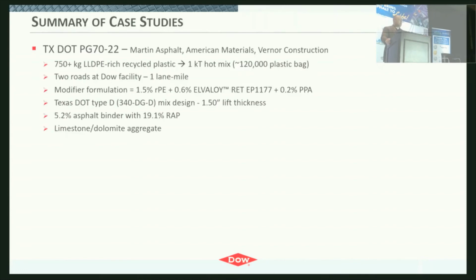So here, just to go through some case studies, basically the partners here were Martin Asphalt, American Materials, and Vernor Construction, all based in South Texas. This 70-22 that was targeted, in this roughly 1 lane mile project, there was 750 kg of recycled material used. And so this is an equivalent weight of around 120,000 plastic bags. We did not use plastic bags in this, but just an equivalent weight. That's your single-use grocery bags that are really not single-use. Around 120,000 were used for a lane mile.